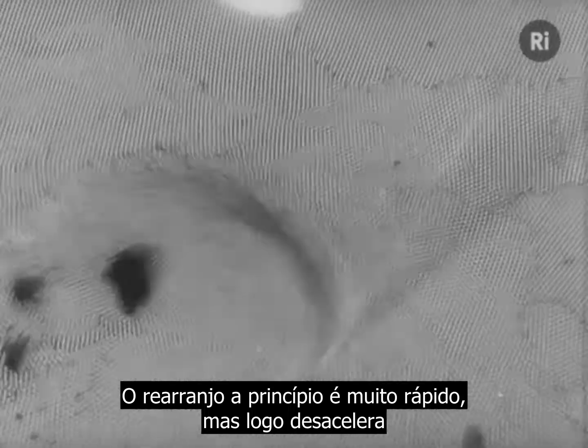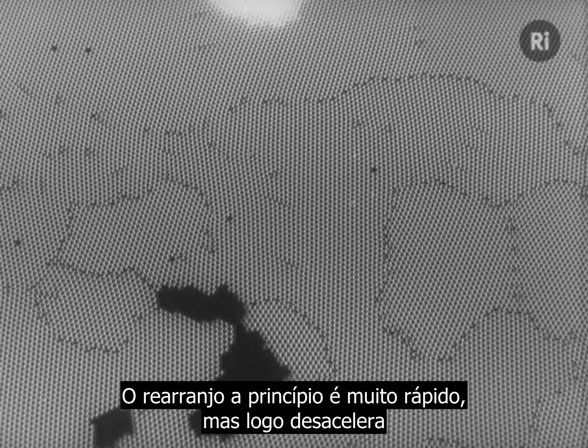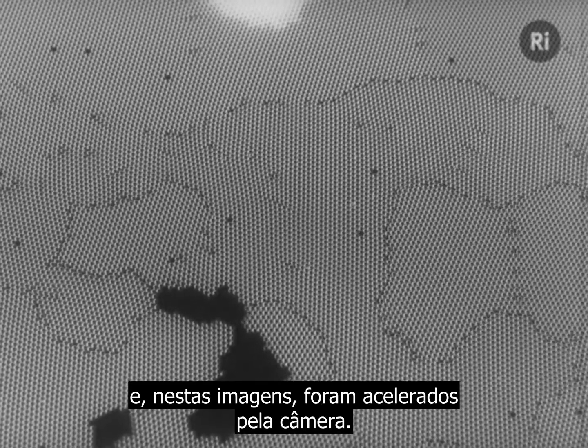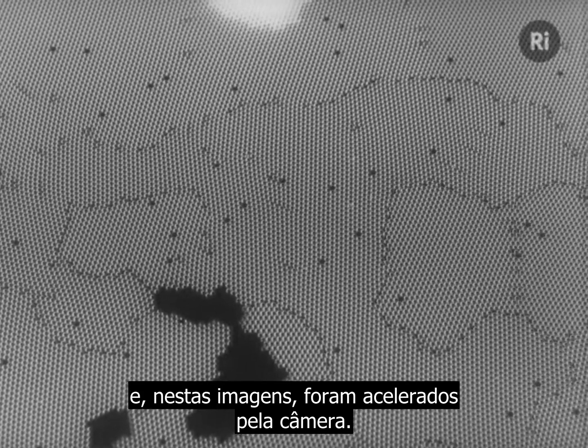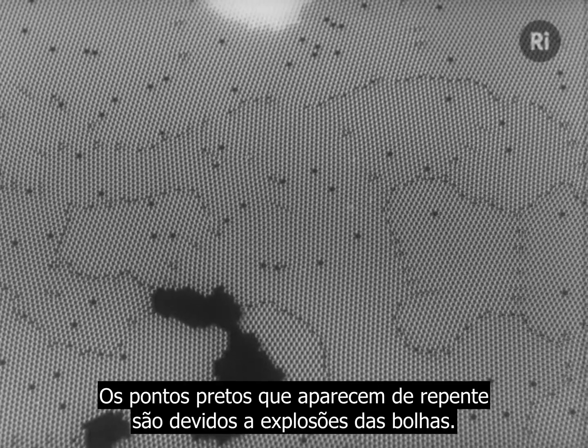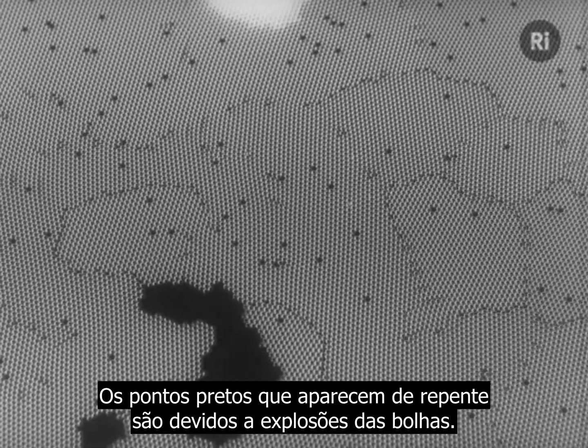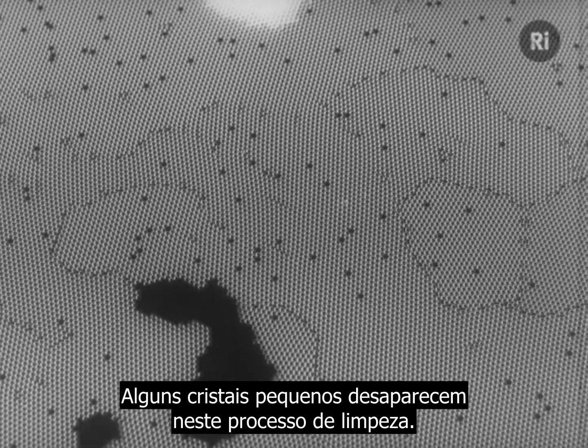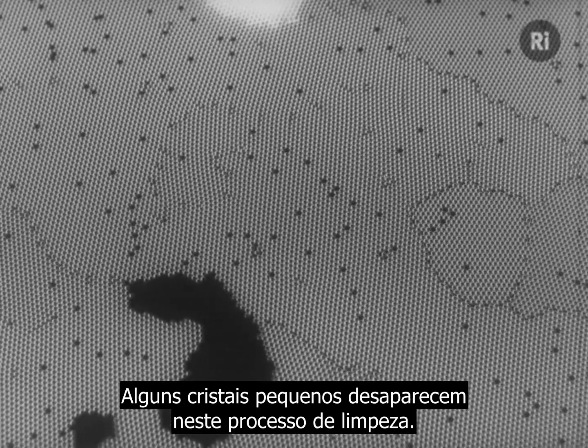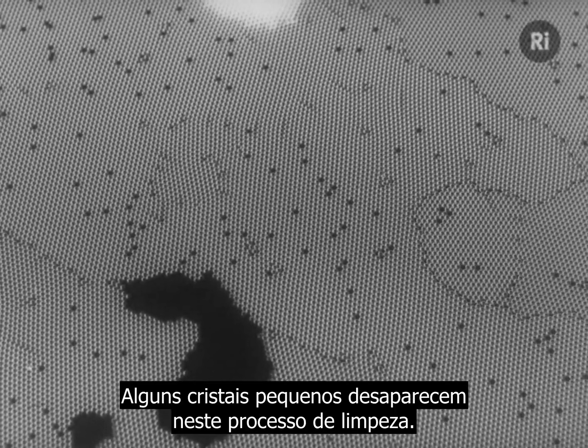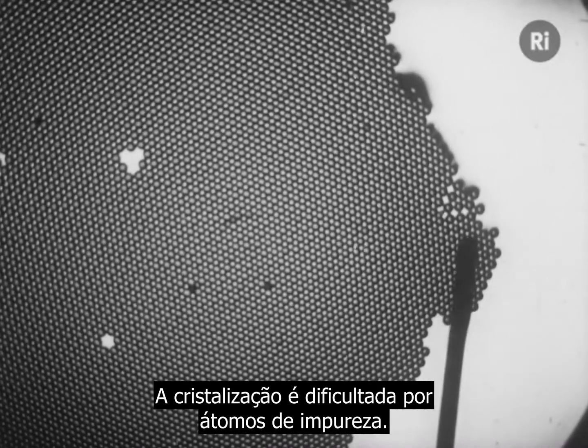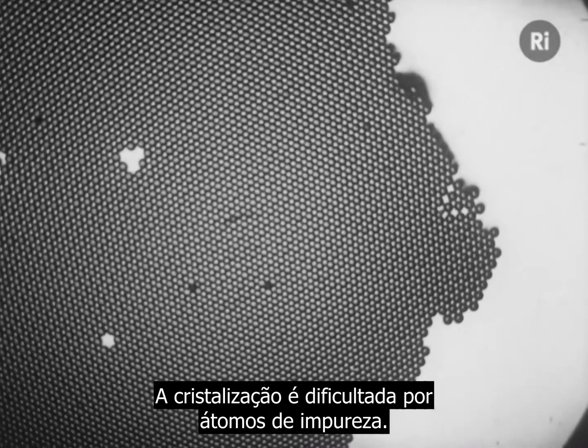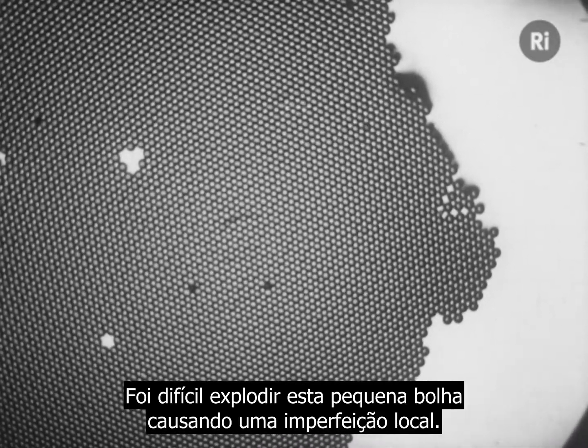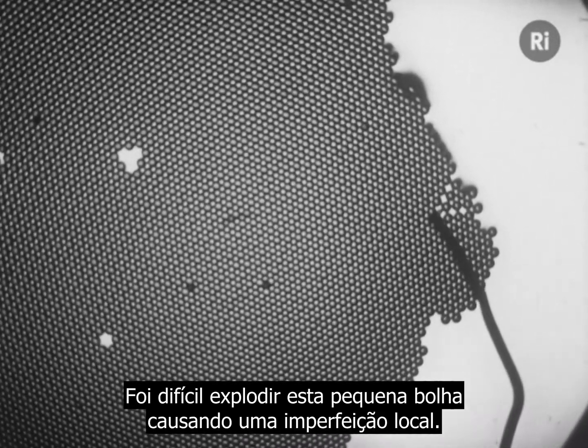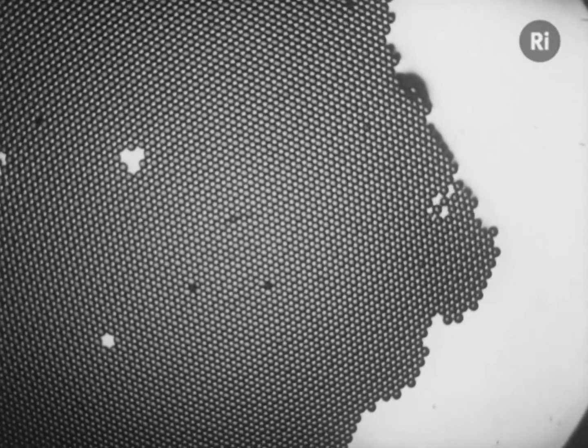The readjustment is at first very rapid, but it soon slows down, and in these shots it's much speeded up by the camera. The black spots which suddenly appear are due to bubbles bursting. Some small crystals disappear in this cleaning up process. Crystallization is impeded by impurity atoms. This small bubble, causing the local imperfection, was difficult to burst.